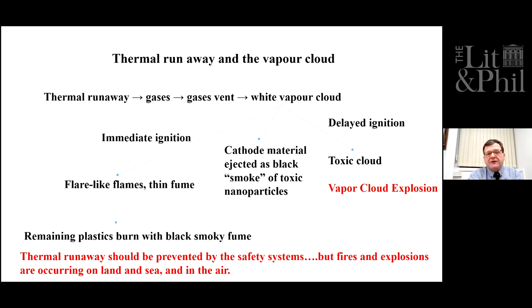So the sequence of events are as shown here. Thermal runaway produces heat and gases. The gases vent. Now, commonly what happens is that the small particles of the cathode, the heavy metal oxides, are vented first as a black cloud that looks like black smoke. And then you get the vapor cloud. If that ignites immediately, in many ways, that's good news. The vapor cloud is replaced by a very thin fume and long flare-like flames. Fire is easy to deal with.